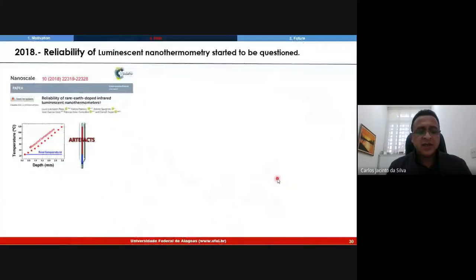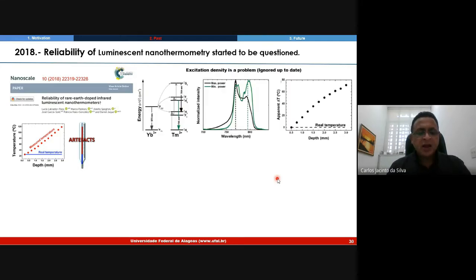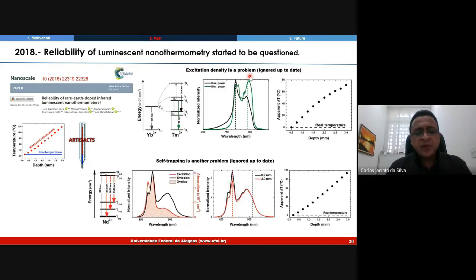Parallel to these excellent works, the reliability of luminescence nanothermometers, principally for in vivo application, started to be questioned. The main issue is the reproducibility of the results obtained and also the spectral and temperature dependence of the optical properties of the tissue. For example, excitation density could be a problem, and it was ignored up to date. The temperature can be so different from that measured. Self-trapping is another problem, and it was also ignored.